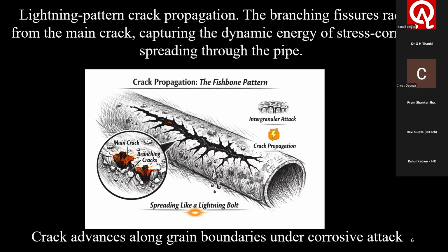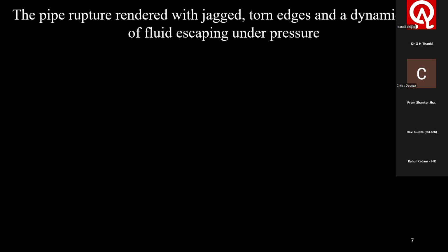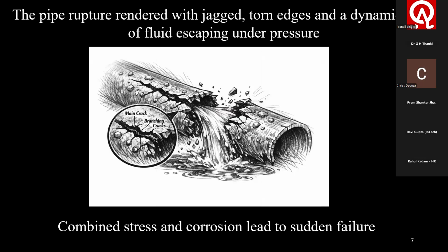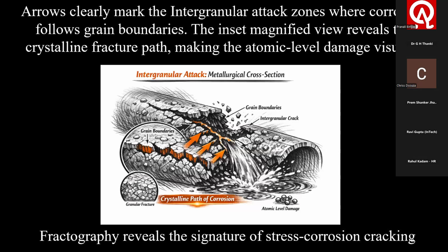The crack advances along grain boundaries under corrosive attack. Next one for you, a little more. The pipe rupture rendered with jagged, torn edges and a dynamic burst of fluid escaping under pressure. This is a combined stress and corrosion leading to sudden failure. And these arrows clearly mark the intergranular attack zones where corrosion follows grain boundaries. The magnified view reveals the crystalline fracture path, making the atomic level damage visible. You can see the crystalline path of corrosion.